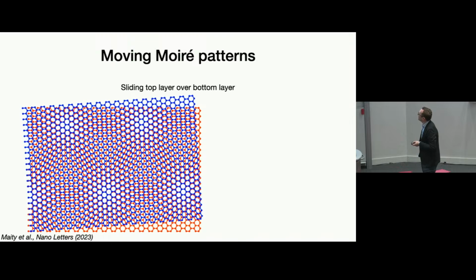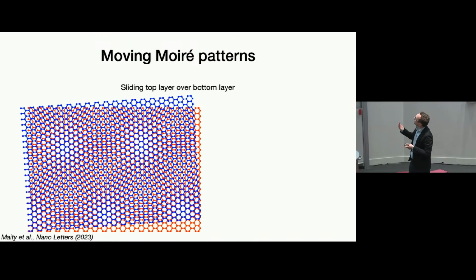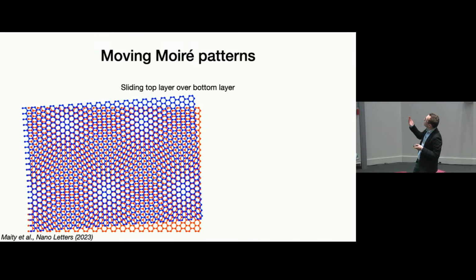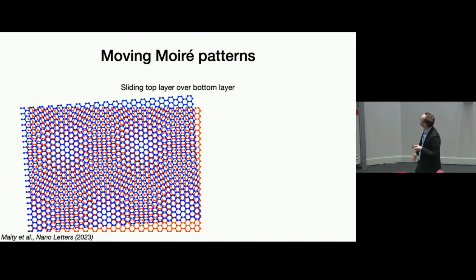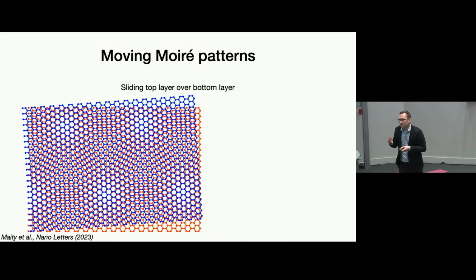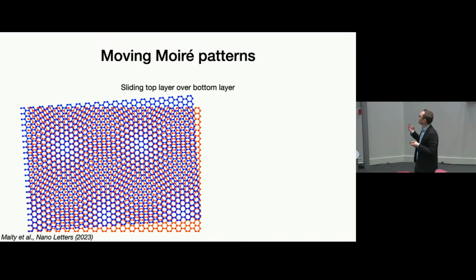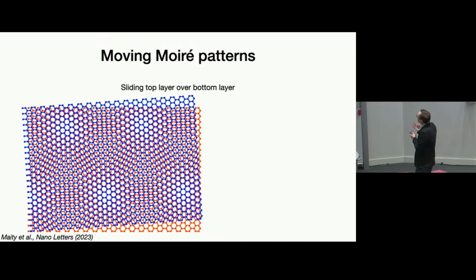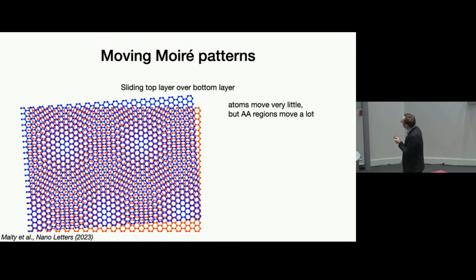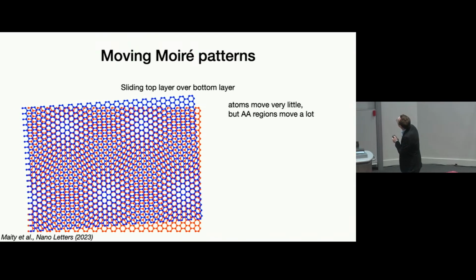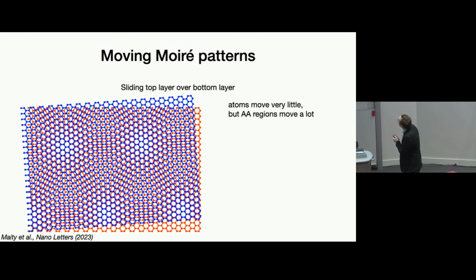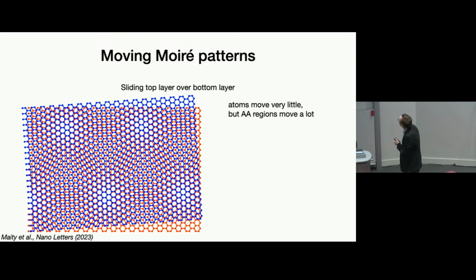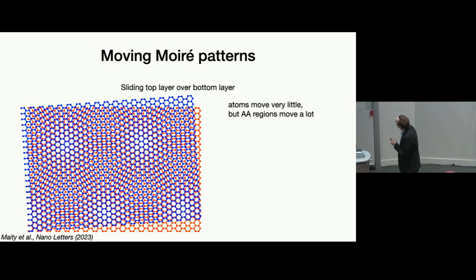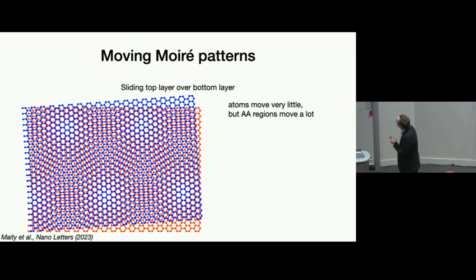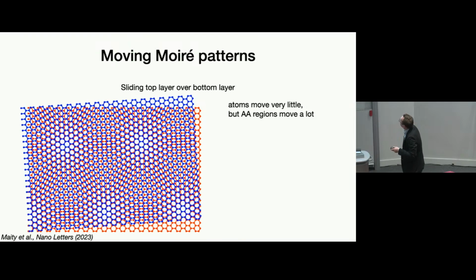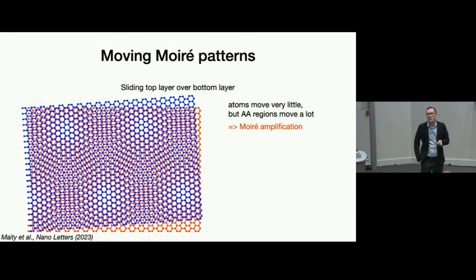And so here, one simple way we can move it is by sliding the top layer over the bottom layer. And there are three important observations that I want to make about this system. The first one is that, when you look at the atoms here, you see that the atoms only move a tiny bit relative to one another. However, when you look at the Moiré regions, they actually move a lot. And this is a phenomenon that's known as Moiré amplification.